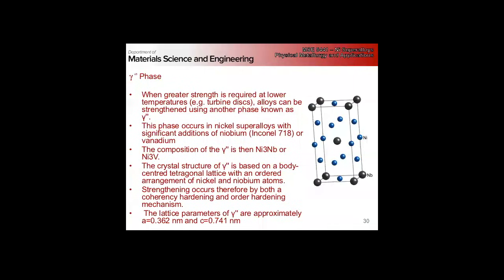Get up, observe. So I mentioned gamma double prime phases. Some superalloys, particularly those with high niobium or vanadium concentrations, such as the ubiquitous Inconel 718, don't form gamma prime, and we use a different phase for strengthening - this gamma double prime - and the structure is based on this nickel 3 niobium or nickel 3 vanadium.